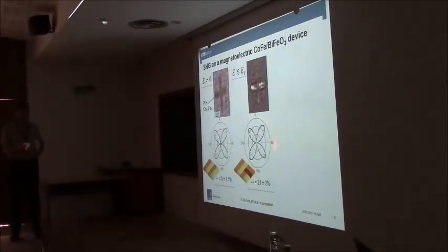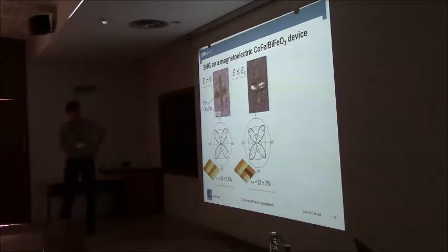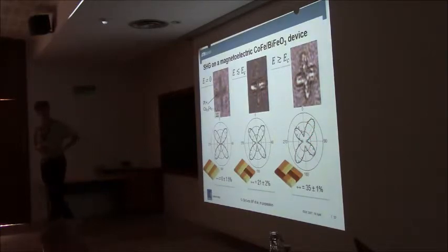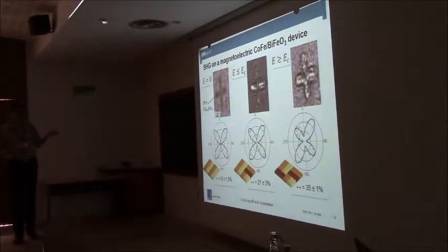And if you analyze this polarization dependence, you can tell that in your ferroelectric bismuth ferrite, you have now induced 21% of a differently oriented domain stripe. And if you increase the voltage, you see it goes up to 35%, and your quadruple lobe deforms more. So we can look at the magnetic structure, the picture that I have shown in the beginning, and at the ferroelectric structure that is beneath and what it has really done in response to the voltage, without having to remove the platinum electrodes.